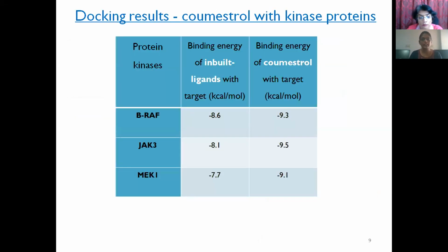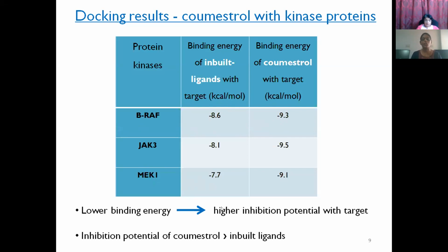Coming to the docking results, from the table it is clear that coumestrol shows strong binding energy with all the selected targets: minus 9.3 kilocalorie per mole with BRAF, minus 9.5 with JAK3, and minus 9.1 kilocalorie per mole with MEK1. Comparing with the binding energy values of the inbuilt ligands: BRAF minus 8.6, JAK3 minus 8.1, MEK1 minus 7.7. Lower binding energy indicates higher inhibition potential, and in all three cases the inhibition potential of coumestrol is much higher than that of the inbuilt ligand.